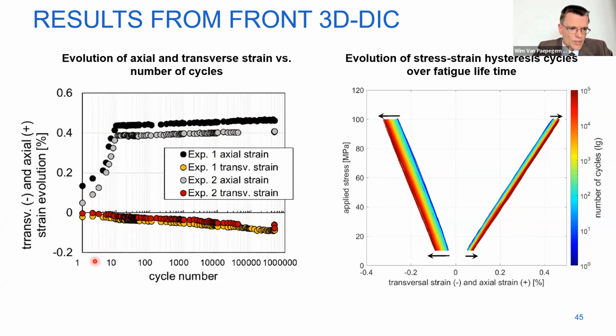Be careful, this is logarithmic scale, so this is the running in of the machine that you see. And then when the machine ramps to the final amplitude, the fatigue test continues and you see a slight increase in the longitudinal strain. On the right, you see basically more or less the same information, but combined with the